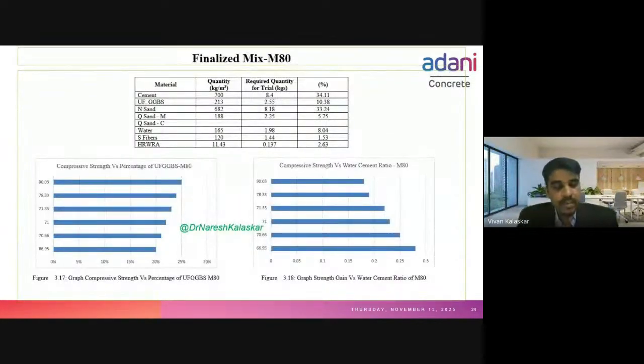If you see the graph trend, when you are increasing the ultrafine GGBS content, your compressive strength is going up. So when we have used ultrafine GGBS 20%, our compressive strength was 66.95. When you are using ultrafine GGBS 25%, our compressive strength was 90 MPa. So ultrafine GGBS or alcofine is an excellent cement replacement for UHPC.